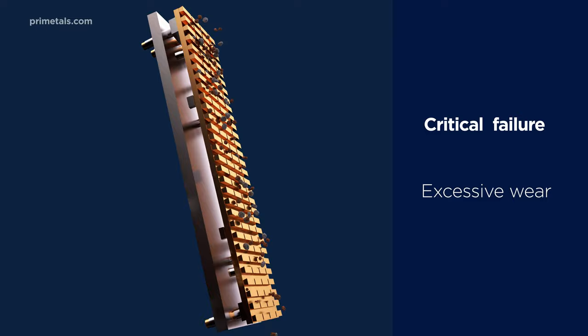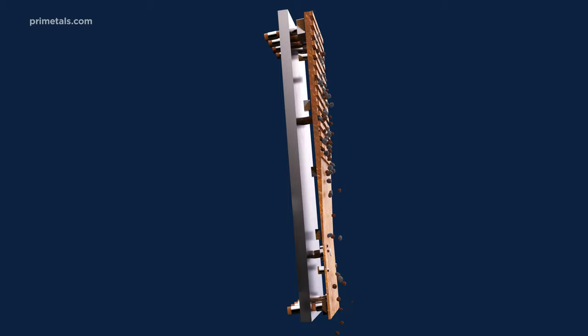The second is excessive wear of the stave surface. This is typically caused by abrasion from burden materials and is often made worse by an incorrect internal furnace profile. It can eventually expose the cooling water channels and cause leakage into the furnace.